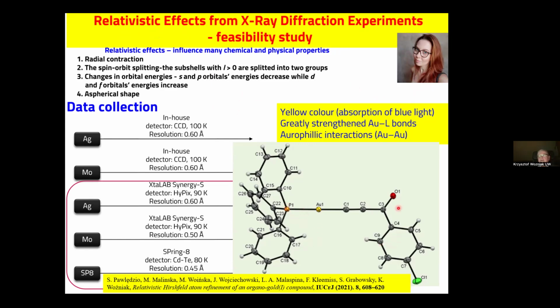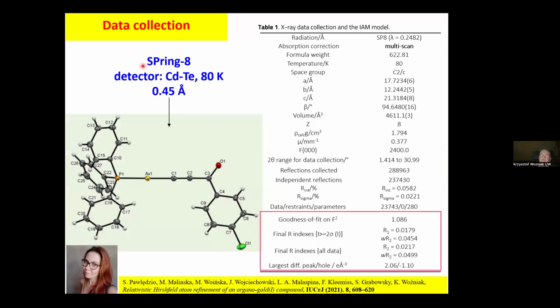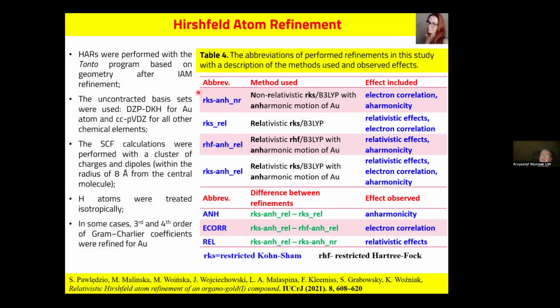So she was studying this kind of system, which is a gold derivative, and we were struggling to get good quality data. And finally, we got them from Spring-8. With this data, we've got 0.45 angstrom resolution, and we performed HAR using lots of different refinements at different